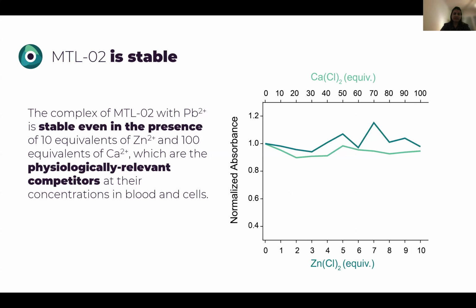And also the metal selectivity. So for example, here, when we incubate the complex that is formed between our peptide and lead with either zinc or calcium, and bear in mind that we are incubating the complexes with 10 equivalents of zinc or 100 equivalents of calcium to mimic the physiological environment and the concentrations in the bloodstream, we can see that the complex is kept intact, which means that MTL-02 in this case does not replace lead with calcium or with zinc. There's practically no interaction between those two essential metal ions and our peptide, and the complex integrity is not being jeopardized.